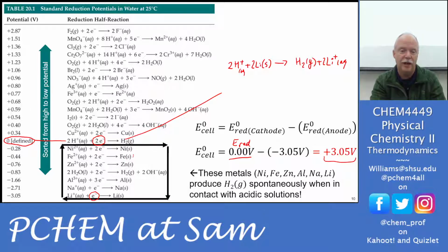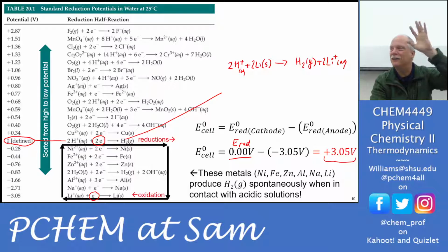They accidentally, up in Boeing one year, they had to shut down Interstate 5, going north and south, where Boeing had pumped acid into a metal tank. They thought it was glass lined. They made a mistake. It wasn't a glass lined tank. It was a steel tank. And this acid started generating hydrogen gas and blew the top off the tank and was venting hydrogen gas.